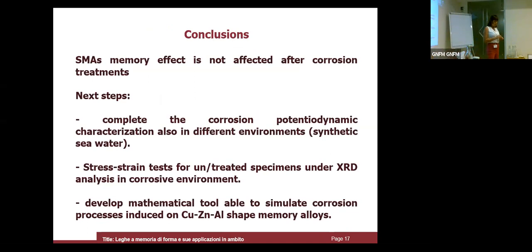Regarding the modeling, in our group we also collaborated with Professor Elena Bonetti. Professor Elena Bonetti developed in the past shape memory models. I think it was a Frémond model. It's called the Frémond model, and it's a phase transition model in which they take into account the transformation of austenite into martensite and vice versa. They consider the difference in the structure because the austenite is a cubic cell and the martensite is a tetragonal cell. So this change in the cell permits the shape memory effect.